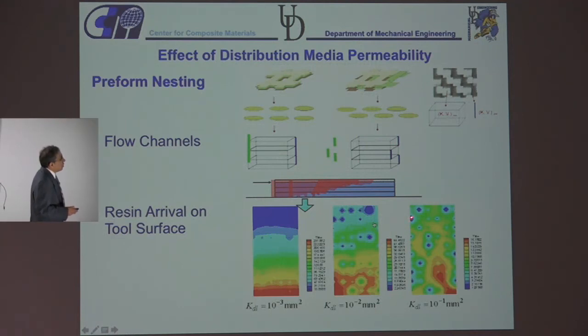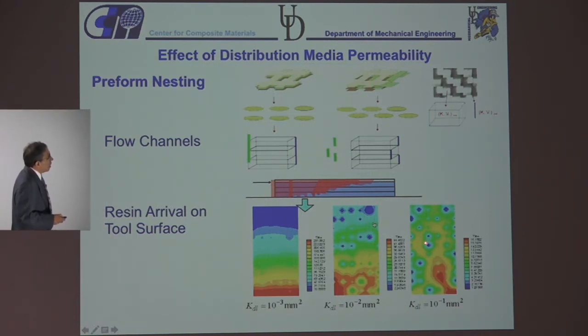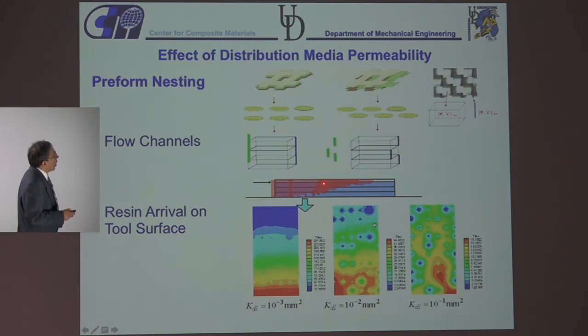The blue is when the resin arrives first, the red is when the resin arrives last. So you're going to get dry spots in here. If you make the permeability of your distribution media 2 orders of magnitude less, you see the flow front at the bottom layer is moving more uniformly. So this is again counterintuitive.